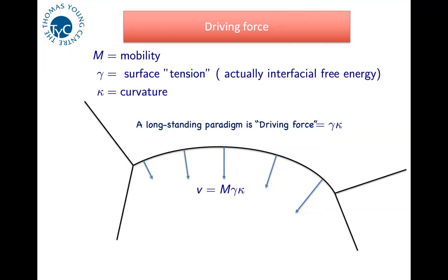Interesting, I thought. Anyway, a paradigm for the driving force of crystal grain growth has been curvature-driven growth based on surface tension, or what I prefer to call interfacial free energy, because it's not really a mechanical tension, and based on the mobility. So if you have a curvature of a surface kappa, then they might simulate it by saying that the surface is going to move with a velocity which is proportional to a mobility and the driving force, which is the free energy of the surface per unit area, gamma, times kappa, the curvature, which, for a two-dimensional surface, would be the mean of the inverse radii over the two principal axes.